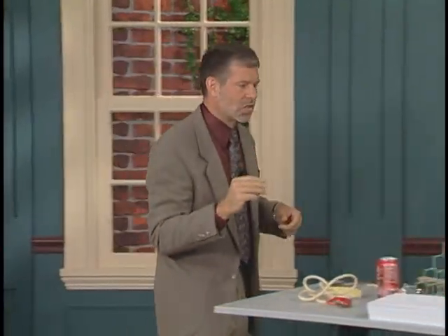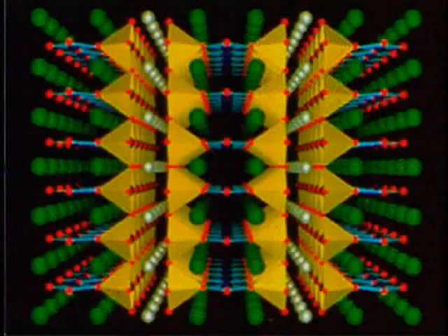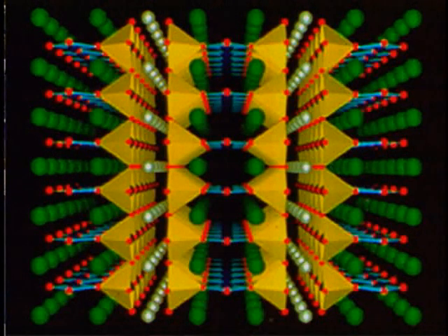So we got this sample by FedEx. Immediately a group of 4 of us began to work on it round the clock. And it turns out the sample was polycrystalline, and there were thousands of tiny crystals. We had to mount up these crystals and X-ray them. And eventually we found one large enough to do the structure analysis. It turns out that the crystal structure was related to an important group of minerals called perovskites. We also found that the composition had a pleasing 1:2:3 ratio of the elements yttrium, barium, and copper. And here's the structure. It's an absolutely gorgeous structure featuring layers of copper and oxygen atoms. It now seems that this layering plays a key role in the mechanism of superconductivity.